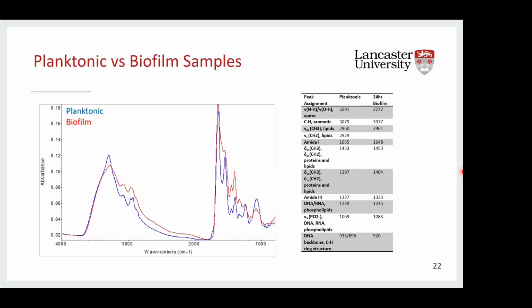As an example, if I show you these two overlaid spectra, we have a 24-hour aged biofilm compared to the spectrum of a planktonic bacteria. Each peak in this spectrum is tabulated, and there are standard tables of these peak assignments from which I can determine this information. Each peak relates to a specific chemical signature within your sample. For instance, if I take this amide 1 protein group, typically this will sit between 1600 and 1700 wave numbers. The exact peak position is controlled by the conformation and type of protein bonds that you have.